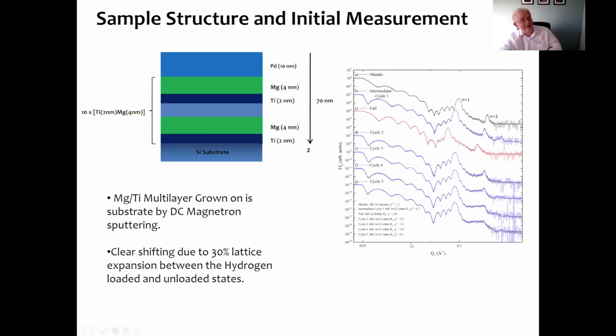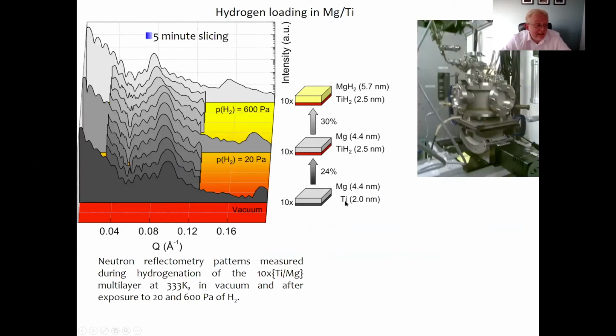Well, lots of things. Bill David and colleagues have looked at it to look at hydrogen absorption in a titanium magnesium multi-layer system. What they found was, if you had titanium magnesium multi-layers and you put hydrogen on, the hydrogen would initially go into the titanium layer below the magnesium before it went into the magnesium layer, which was sitting on top of the titanium. If you made multi-layers of this, the titanium would always be hydrogenated preferentially to the magnesium. And you can see that by the difference in the refractive index that comes from the reflectometry.